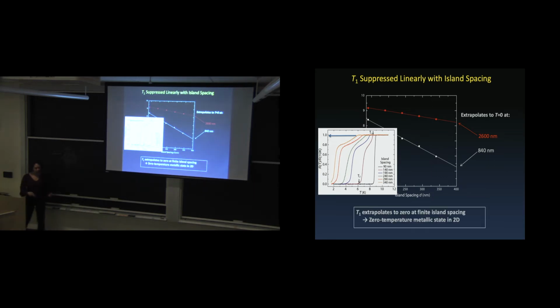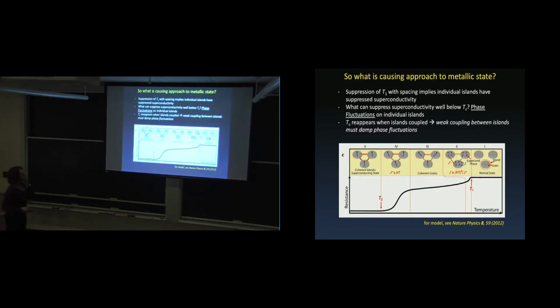So same thing here. Again, this system here, even though it has superconducting islands on it, as you march this point down, you basically reach 0 temperature for a finite spacing, which is an example of a 0 temperature metallic state. Okay. So that's one example of this sort of 0 temperature metallic state that you can see in these sort of phase-separated systems. Now, we can ask, what causes this approach, and basically, there have to be some sort of phase fluctuations on the islands, which is damped by a weak coupling between the islands, even though it's not coherent. And then at this point, you have coherent coupling between the islands as it transitions to actual superconducting state.